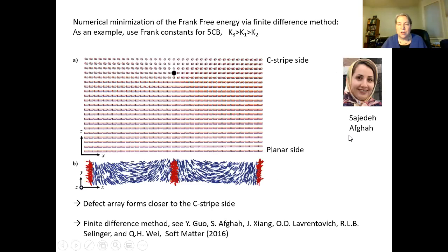So a student working with me, Sajedeh Afghah, who is now at Microsoft, she did numerical simulation. Now, we didn't know the Frank constants for their liquid crystal, so we just used the ones for a common liquid crystal, 5CB. If the C-stripe side is on the top and the planar side is on the bottom, the disclination line is right in the middle coming out of the board, we could figure out what the director field is. And we just did that by minimizing the Frank free energy, which describes the energy of elastic deformation of a liquid crystal, using a simple finite difference method. So that's not rocket science, but it's an important piece of the puzzle here. So not the main part of her dissertation, but she did that to help us out.